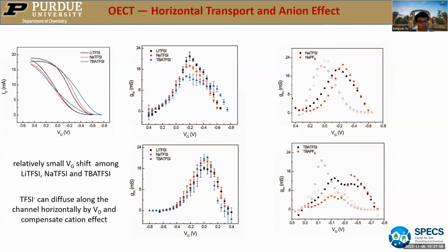So why? Because in our spectral EChem, there should be a large difference. But in OECT, the difference is not as large as before. The reason is that in the OECT, we have a drain voltage. So TFSI, as an organic ion, is easily diffused along the channel horizontally by the drain voltage. So it will compensate the cation effect. Finally, it will just mitigate the difference between the three TFSI cations.